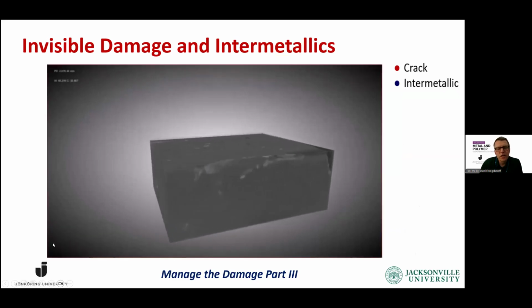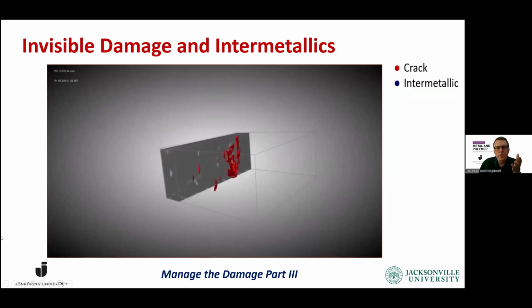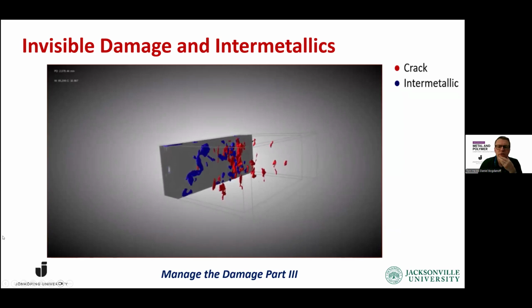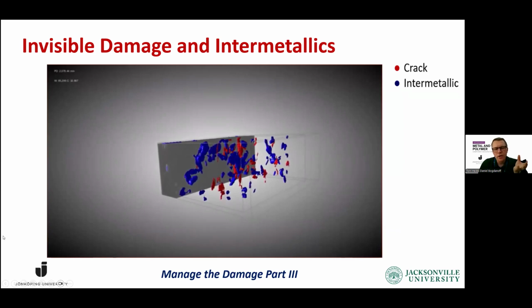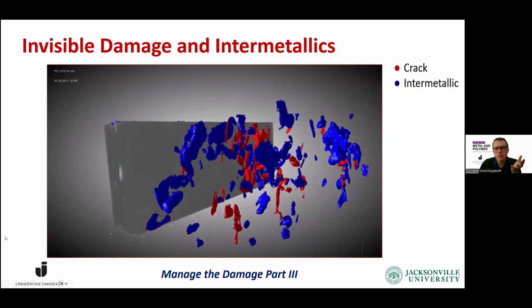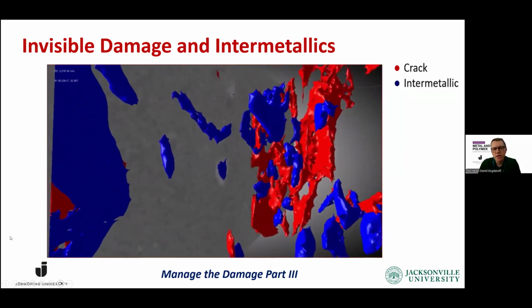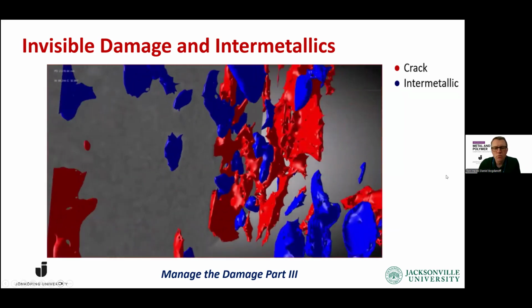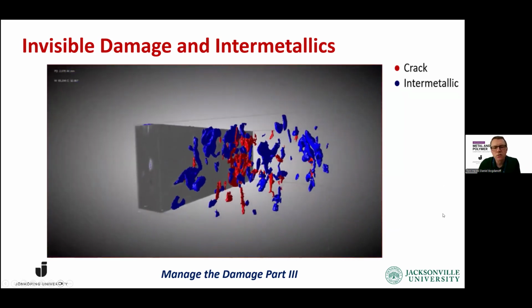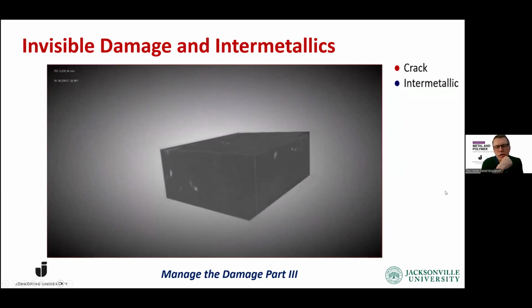If we go to the video in the next slide, what we see on the left side here is the propagating crack front. And when it starts to slice, it will now add all the cracks. What we observed is that we have a lot of small secondary cracks everywhere in front. And they are not directly linked to the intermetallic phases in this case. So this is clear evidence that we have a lot of small bifilms opening up like cracks that will assist the propagating crack front and coalesce with the previous crack. So we will have a lot of small cracks competing for the fatigue failure.